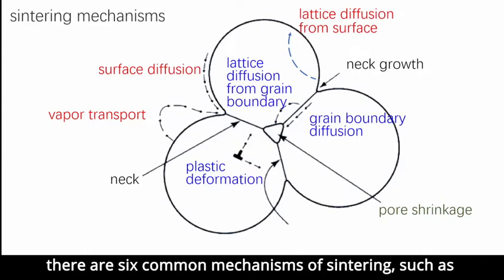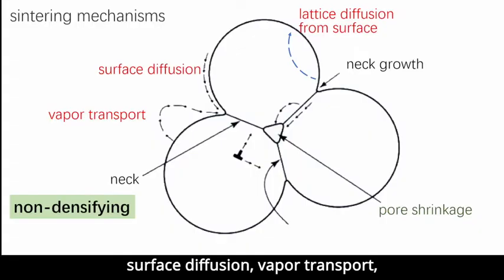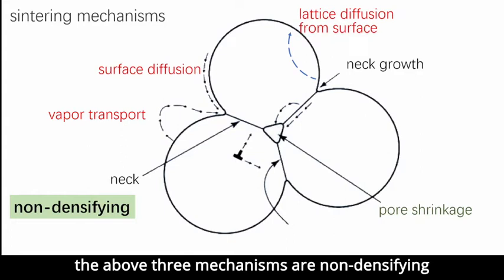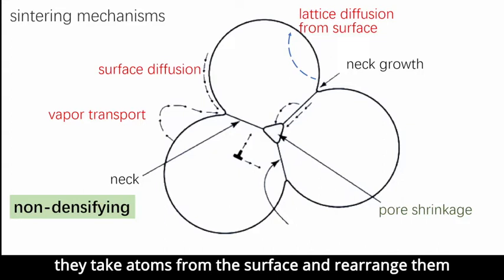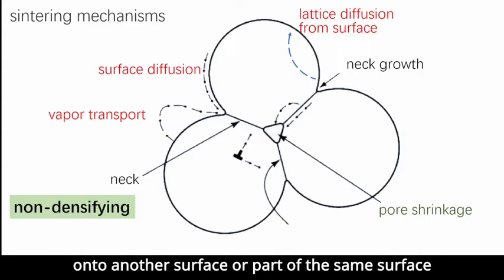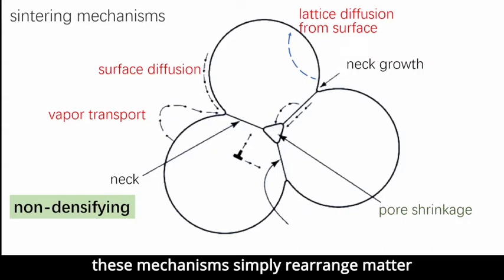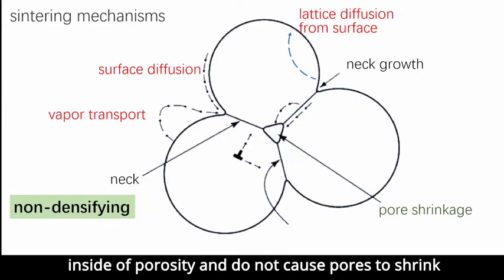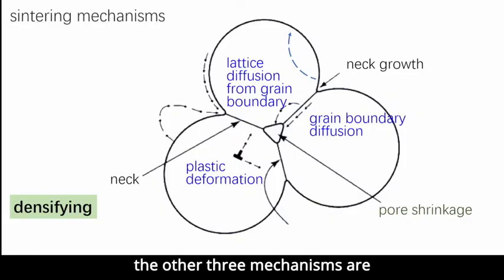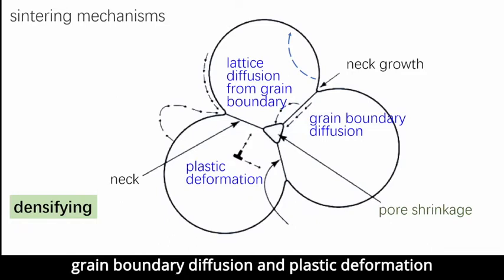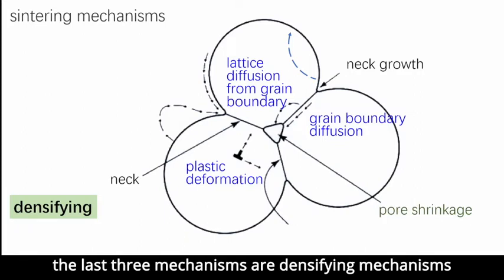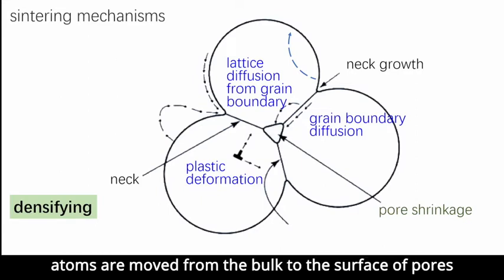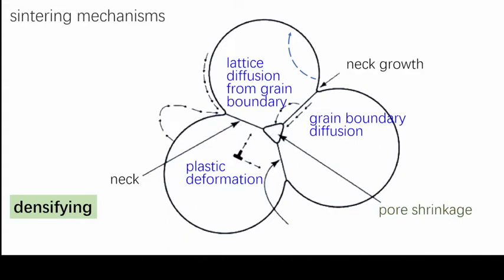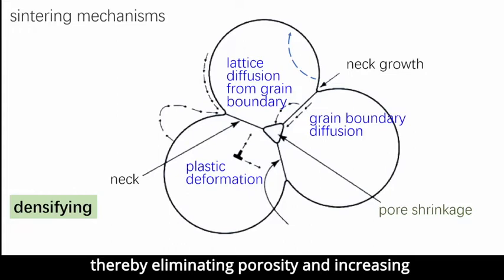There are 6 common mechanisms of sintering, such as surface diffusion, vapor transport, and lattice diffusion from the surface. The above 3 mechanisms are non-densifying. They take atoms from the surface and rearrange them onto another surface or part of the same surface. These mechanisms simply rearrange matter inside a pore and don't cause pores to shrink. The other three mechanisms are lattice diffusion from the grain boundary, grain boundary diffusion, and plastic deformation. The last three mechanisms are densifying mechanisms. Atoms are moved from the bulk to the surface of pores, thereby eliminating porosities and increasing the density of the sample.